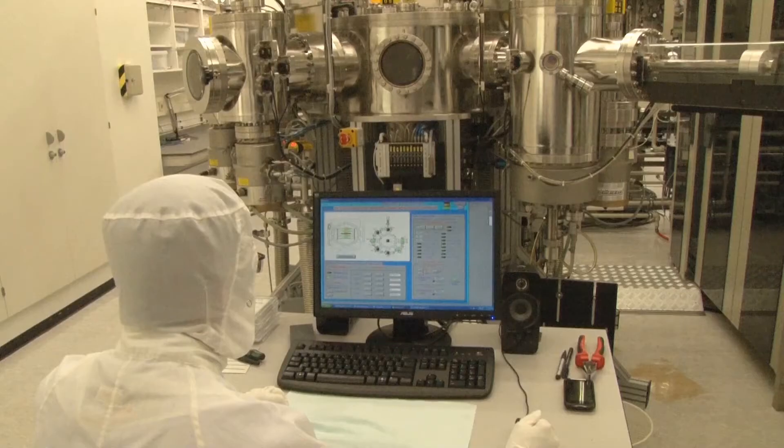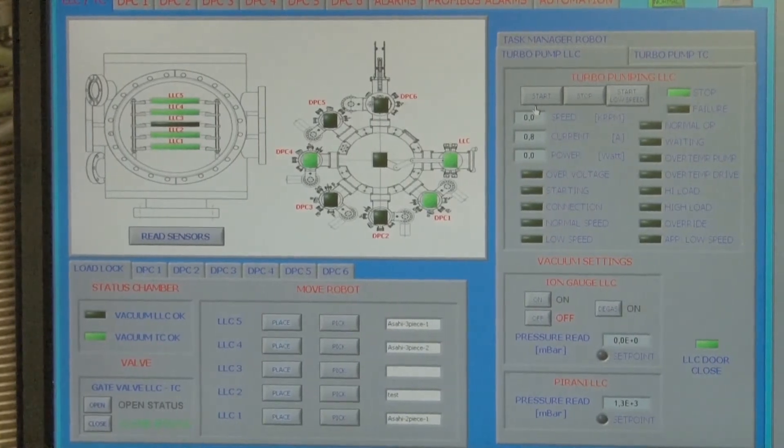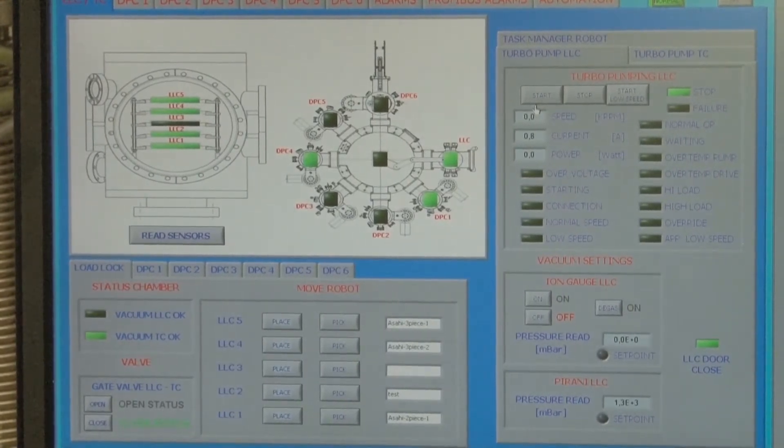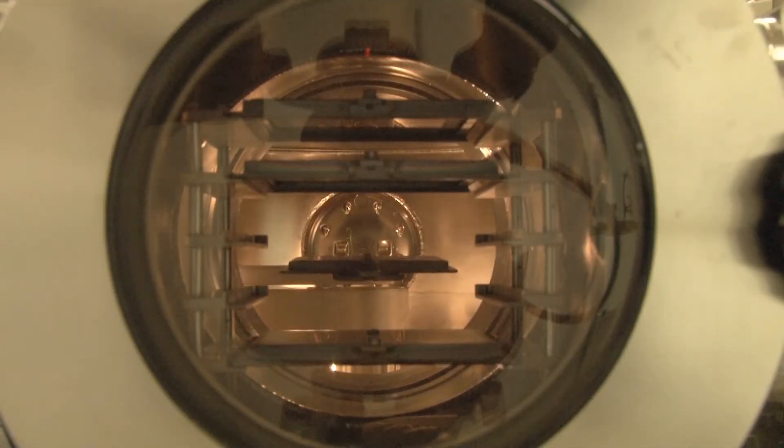Typical precursor gases in the deposition plasma are silane diluted with hydrogen. An RF bias between the electrode plates generates a plasma. The silane is dissociated and the silicon contained in radicals and ions are deposited on the substrate. Adding diborane or phosphine to the plasma makes the films P-type or N-type. Increasing the hydrogen content makes the films nanocrystalline instead of amorphous.